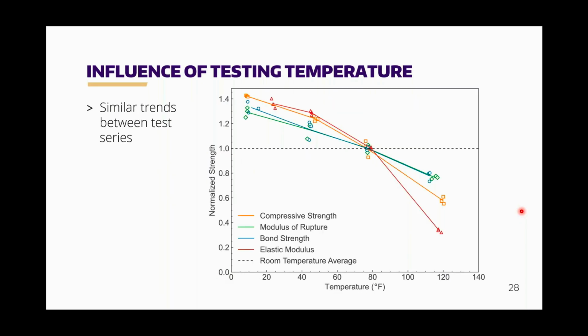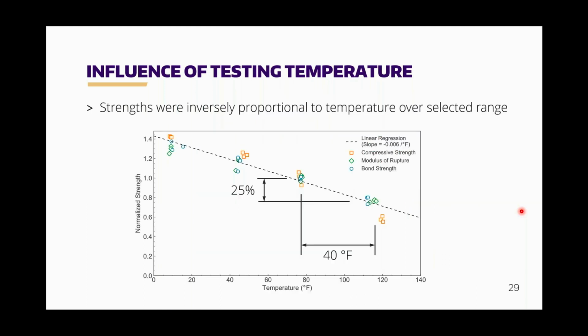Again, we normalized these. In this case, our 1.0 is at room temperature. And again, we're seeing that all of these properties are exhibiting similar behavior with temperature, so you're not having one that's significantly different than the rest. We said, this looks vaguely linear. Can we plot this to a line, a linear regression? And looking at compressive strength, modulus of rupture, and bond strength, just as a generic summary, you get a 25% change in strength for every 40 degrees Fahrenheit. So those are some numbers to throw out there when you're thinking about whether this would be good for the geographic area in which we could apply this.